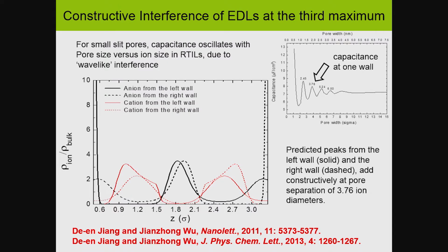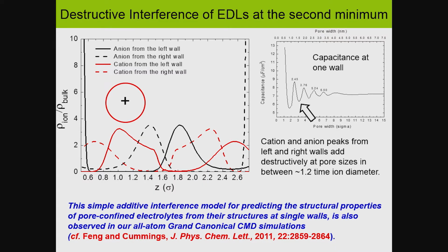What's giving rise to this is simply what Esther asked yesterday: at 3 ion diameters, you can fit 3 ions into the pores, and at less than 3 ion diameters, you get interference. This is an additive property of the double layers at the two interfaces, interacting in a wave-like interference behavior.